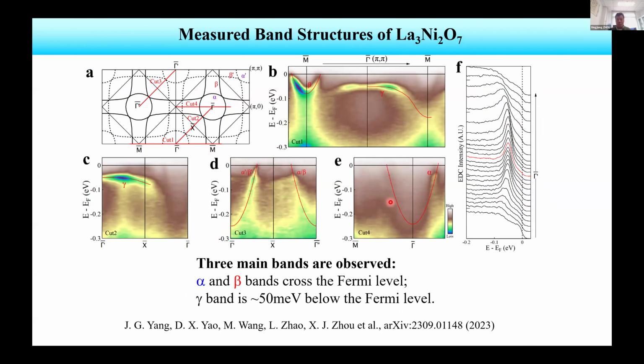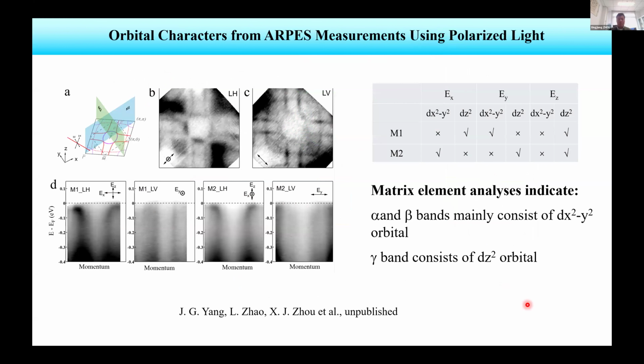But also, particularly near the pi points, we see a very flat band. This band is about 50 millivolt below the Fermi level, and you can see there's some EDC peak here. So this is the flat band near the pi points. This is a prominent feature we observed in the lanthanum 327 system.